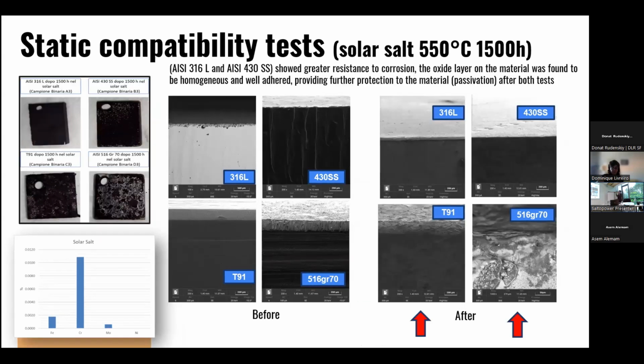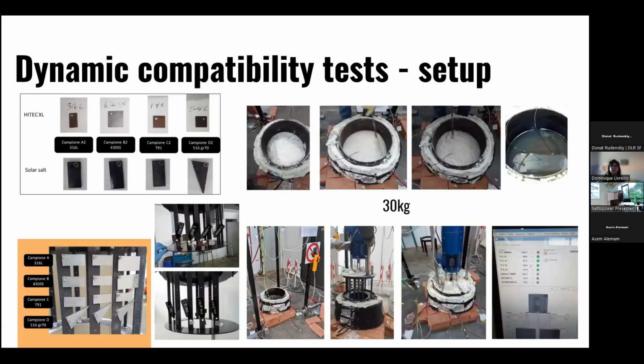while we performed the same test with the same kind of steels with solar salt at 550 degrees for the same amount of time. And as you can see also in the picture, when we picked up the steels and then performed the analysis before and after, we have a lot of holes in the oxide layers. And that states that especially the carbon steel cannot be used at very high temperatures. So moreover, we moved on and we decided to perform some dynamic compatibility tests using a facility that can contain 30 kilograms of salts.